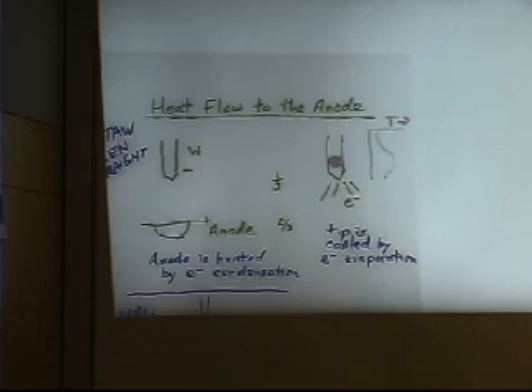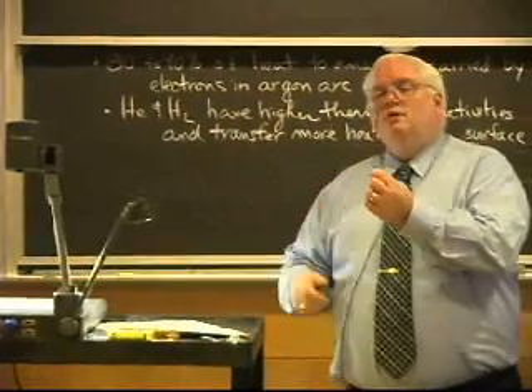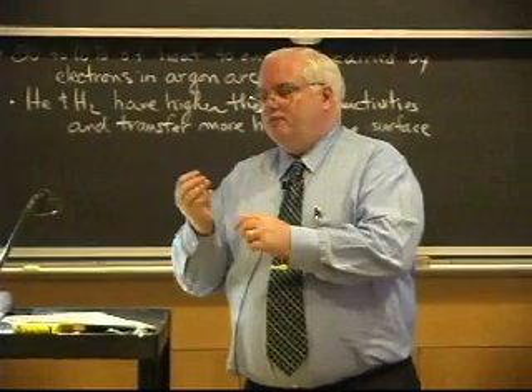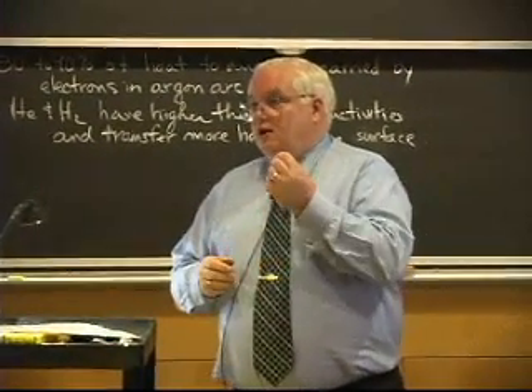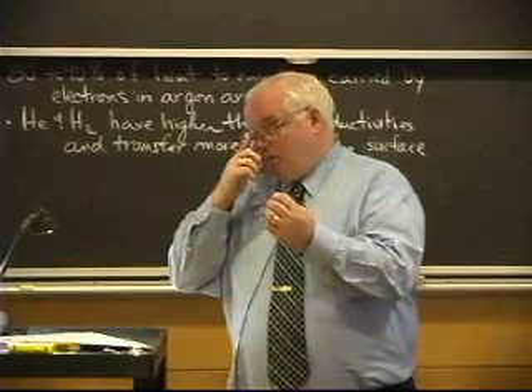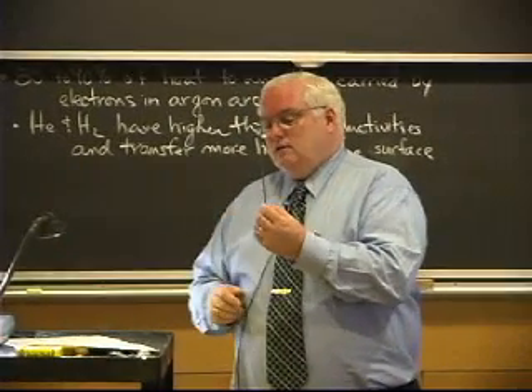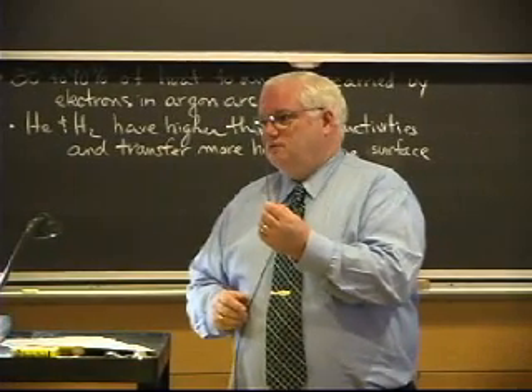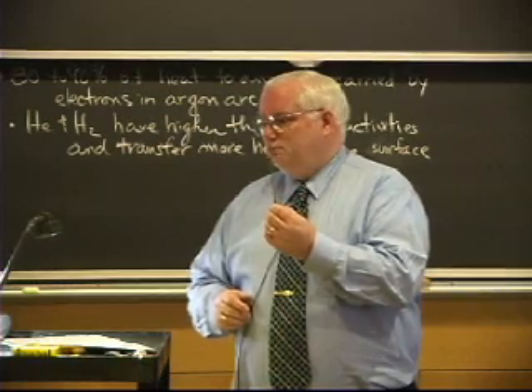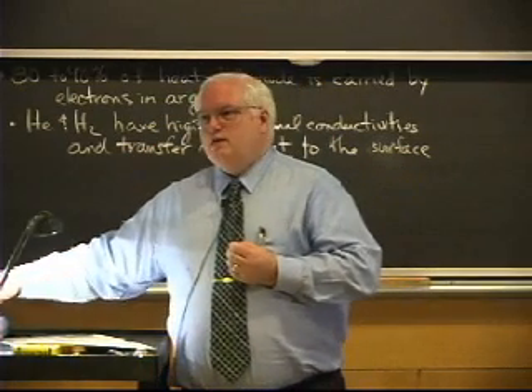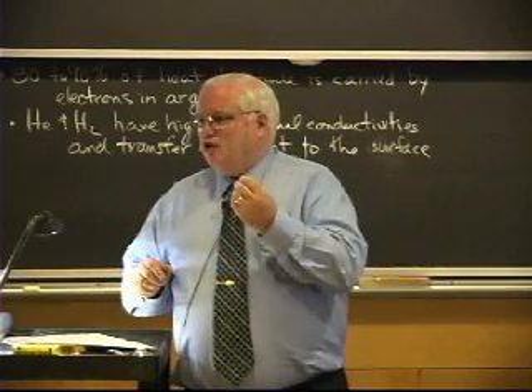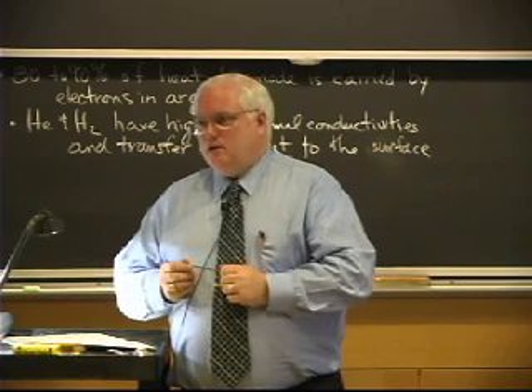It turns out this process can be run either way, but those tungsten electrodes that we just passed around, if I run this in DC electrode negative, might take 200 amps before I would melt the tip. If I run it in electrode positive, it may only take 100 amps before I melt the tip, because I'm getting 2/3 of the heat up here and 1/3 down here. The amount of current I can carry depends on the polarity of my tip.